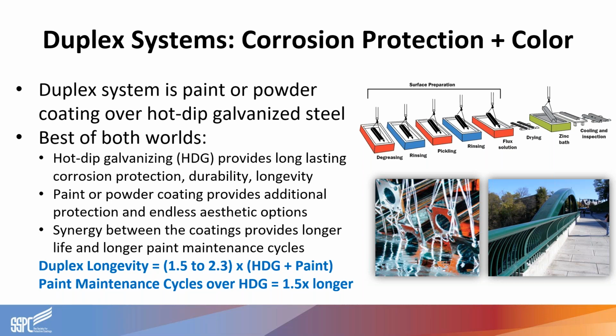But duplex systems are unique in that there is a synergistic effect that occurs between the coatings. How that works is the exterior layer of paint or powder coating will slow down or prevent the rate at which the hot dip galvanizing is consumed. And then once that paint layer has weathered down or become damaged, the zinc beneath will be able to provide cathodic and barrier protection as well. As a bonus, the hot dip galvanized coating prevents underfilm corrosion, and that actually allows paint to last about 50% longer than it would if that same coating was applied over bare steel. And the final result from that is corrosion protection that lasts 1.5 to 2.3 times the sum of the paint life and the galvanizing life if no maintenance were to be performed.